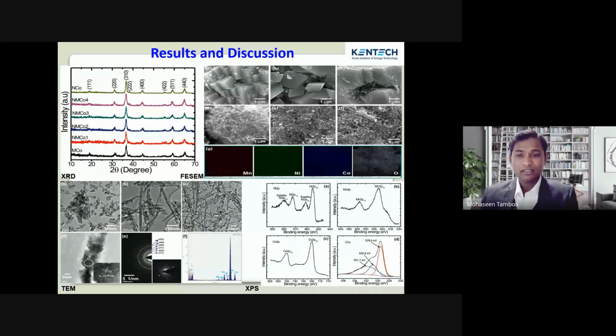You can see the XRD figure, a comparison of XRD patterns of the different electrode materials like nickel cobalt oxide and manganese cobalt oxide. For manganese cobalt oxide we have given the label MCO. When 20% is substituted by nickel, we gave the label 1, 40% is 2, 60% is 3, 80% is 4, and pure NiCo2O4 is 5. This is the comparative XRD pattern of nickel manganese cobalt oxide samples with different ratios of nickel, and all the diffraction peaks can be indexed to cubic MnCo2O4 spinel structure. No impurity peak was observed here.